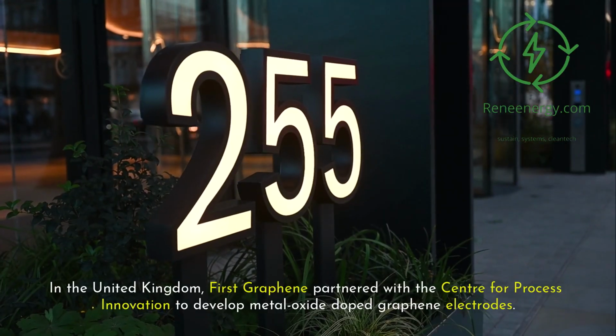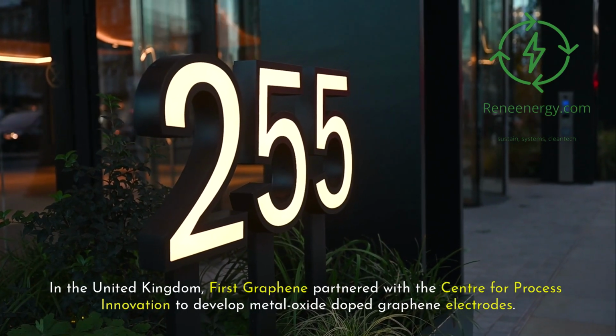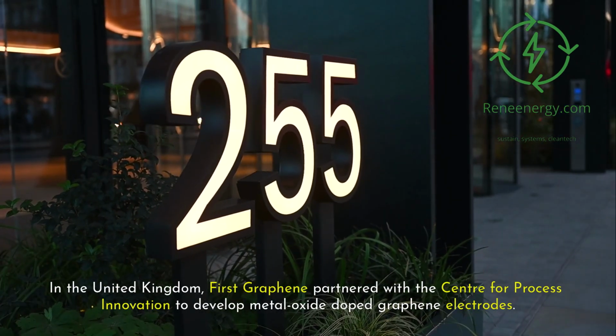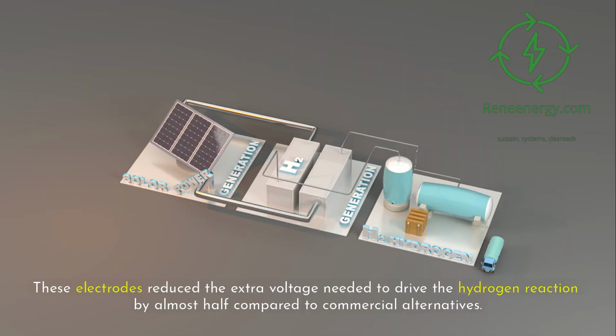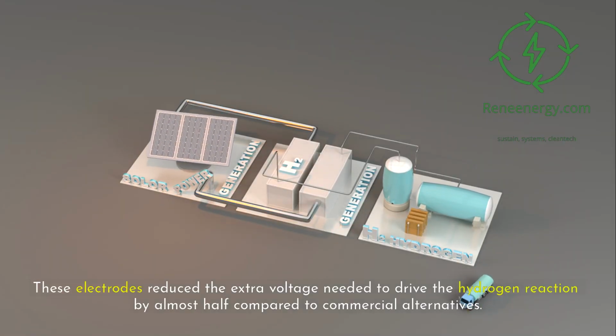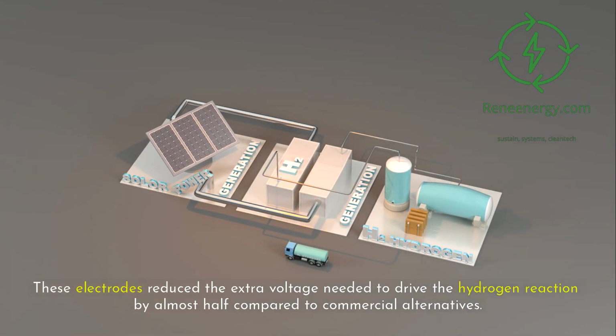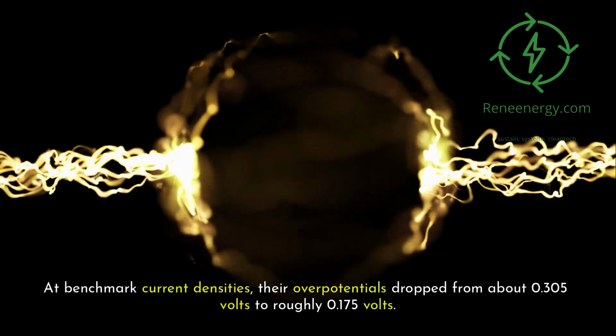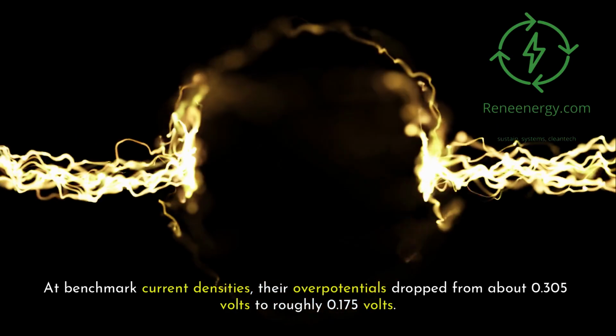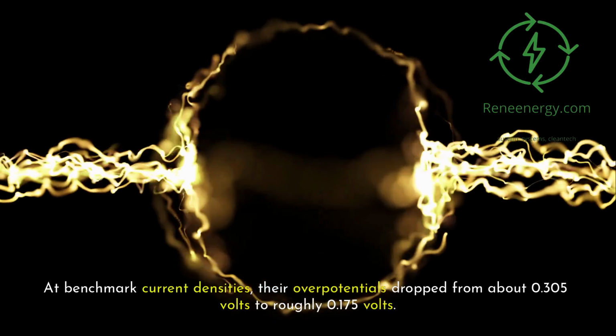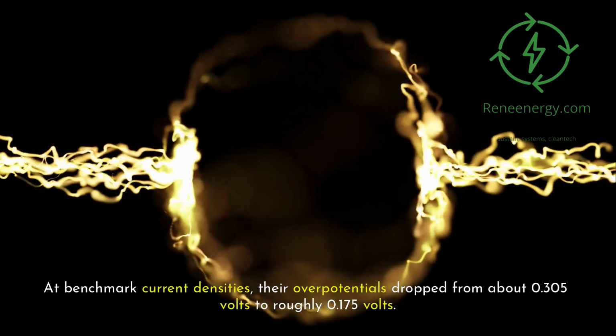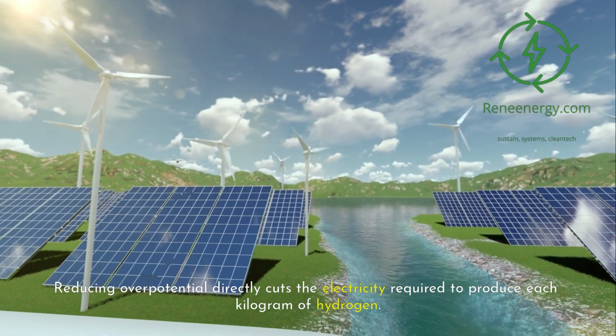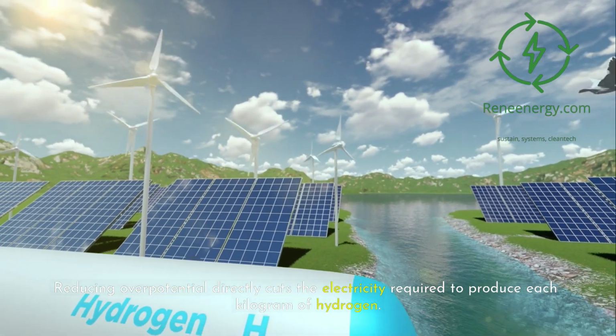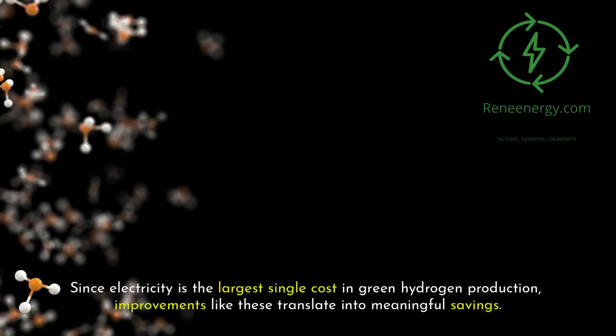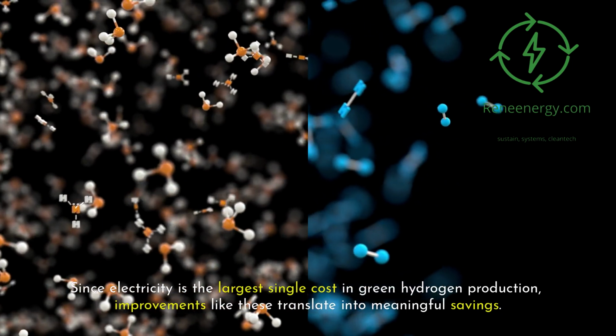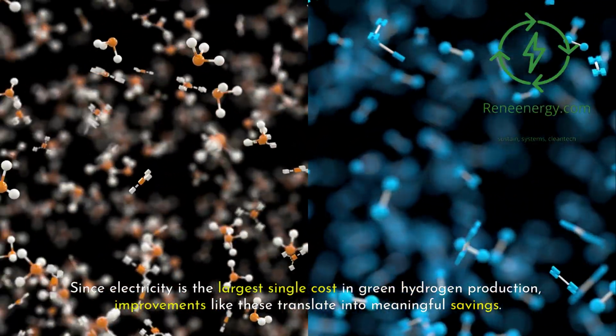In the United Kingdom, First Graphene partnered with the Center for Process Innovation to develop metal-oxide doped graphene electrodes. These electrodes reduced the extra voltage needed to drive the hydrogen reaction by almost half compared to commercial alternatives. At benchmark current densities, their overpotentials dropped from about 0.305 volts to roughly 0.175 volts. Reducing overpotential directly cuts the electricity required to produce each kilogram of hydrogen. Since electricity is the largest single cost in green hydrogen production, improvements like these translate into meaningful savings.